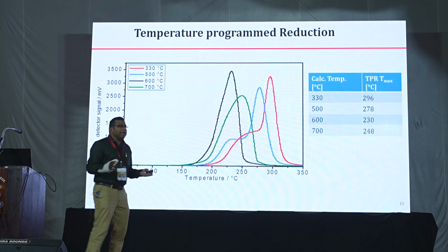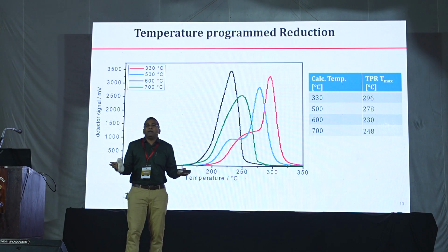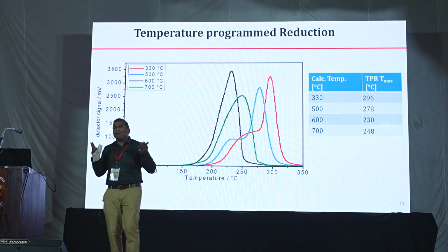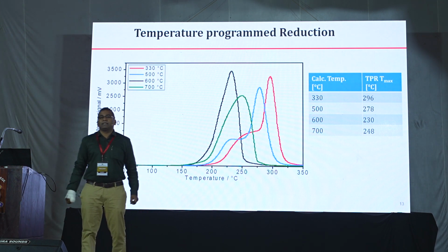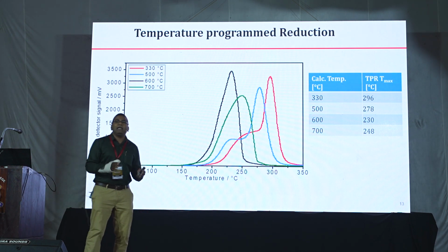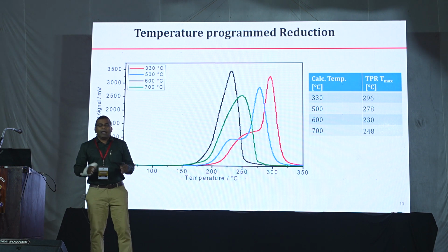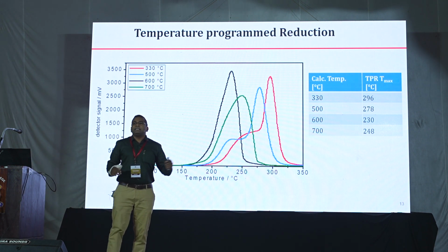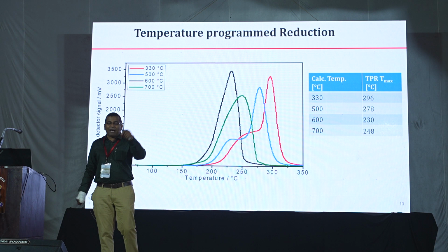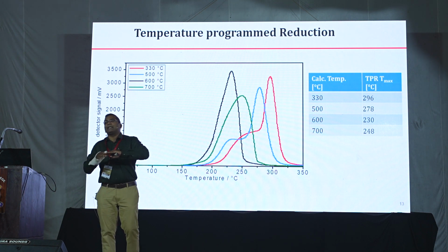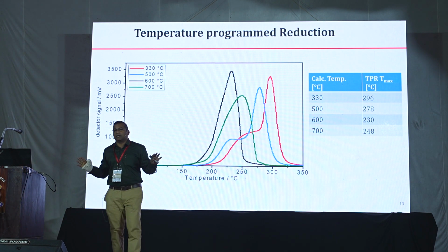When I was in the initial days, I was very curious. If copper is the active phase, why don't we take only copper precursor and start? Then I took a highly active copper precursor alone and started the reaction. Just in 10 minutes time, after getting the first run, the catalyst lost all activity.